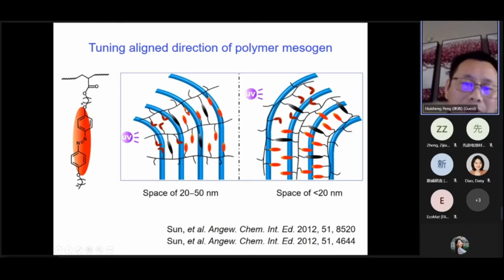If, for the composite materials, the distance between two carbon nanotubes is higher than 20 nanometers, the azobenzene mesogen is aligned along the length direction of the carbon nanotubes. Under UV light, they will bend toward the light source, so the shape change will be like this. However, if the distance is reduced to 20 nanometers or lower, then the mesogen will be aligned perpendicular to the length direction, and in this way under UV light the composite material will bend away from the light source. So it's very simple to control the bending direction by just varying the spacing between carbon nanotubes.